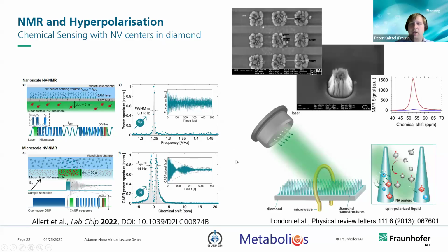conventional NMR, but also you can use this possibility to manipulate your system to transfer the polarization from the NV centers into a liquid, and by that polarize this liquid. And this is shown here. So you have an NMR signal or an MRI signal, for example, that is based on the thermal polarization in blue here. And you can hyperpolarize, so you transfer polarization from the NV to, for example, a 13C spin in a surrounding liquid. And with that, you drastically increase the signal, making it easier to detect it.